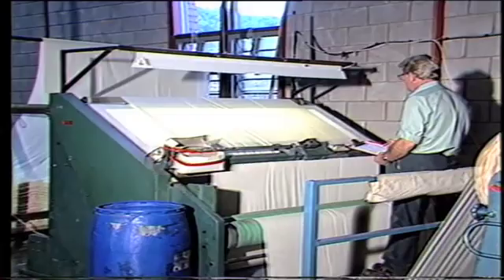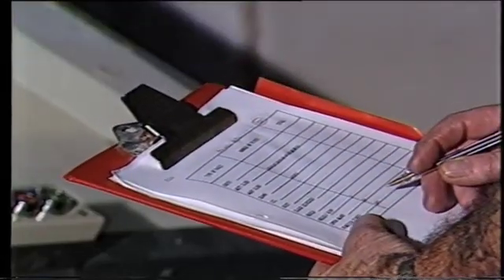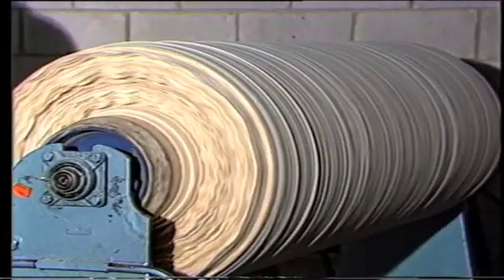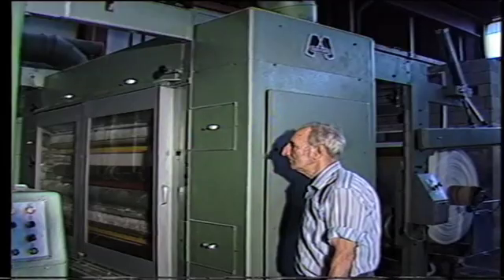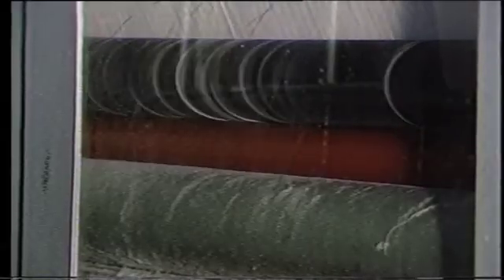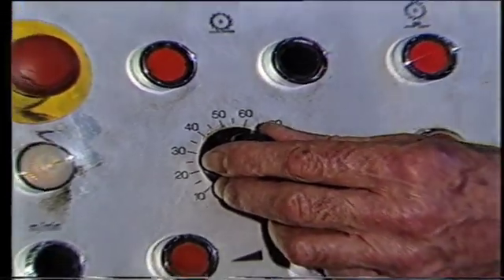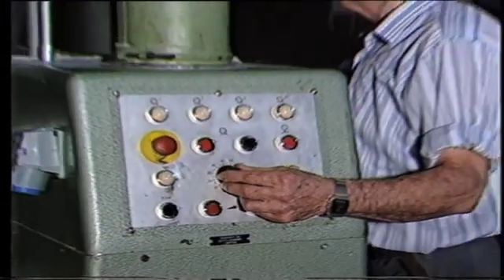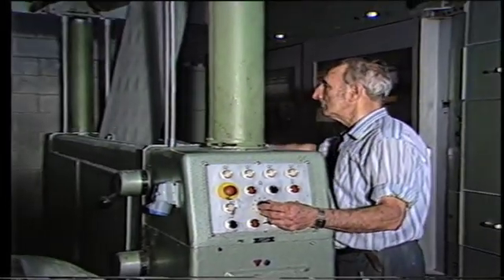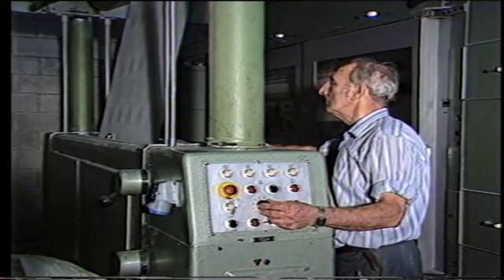At this stage, the cloth is visually inspected for holes, rips, tears, mould, rust marks and weave faults. It is then wound onto a large roll, ready for the next process, cropping. The cropper removes long surface fibres from the cloth by a shaving action. It also removes dust by beating the cloth. Most fabric at TextPlan is cropped, as it improves the surface texture of the fabric for dyeing and printing by making it smoother and reducing the dust content.